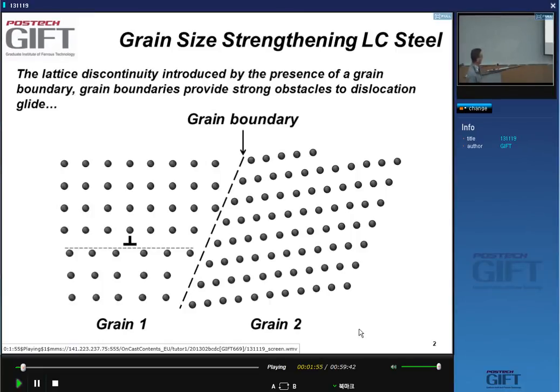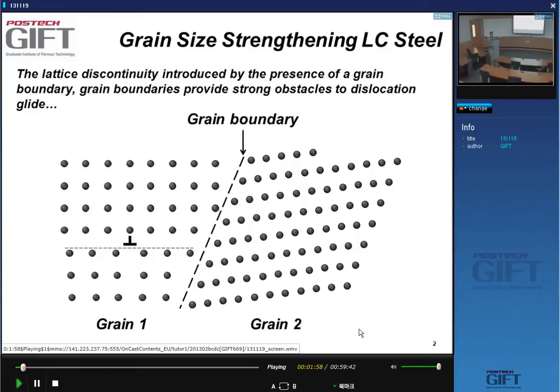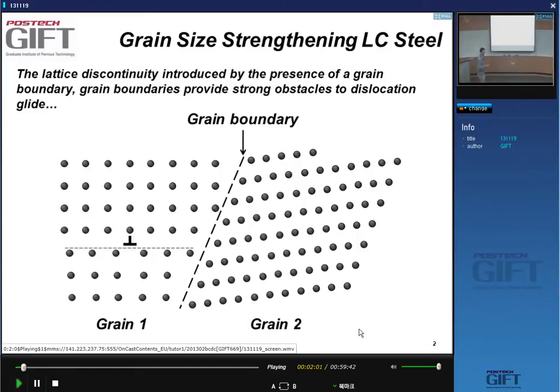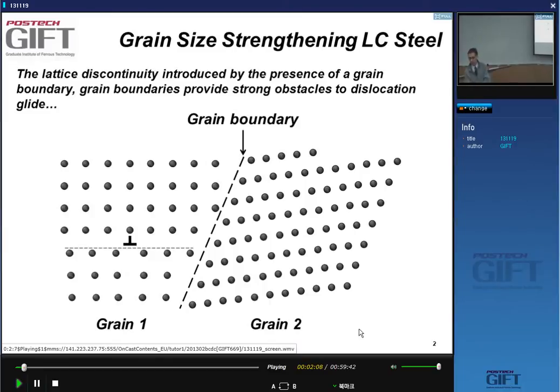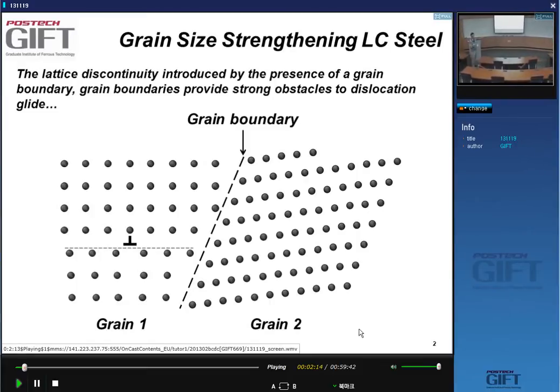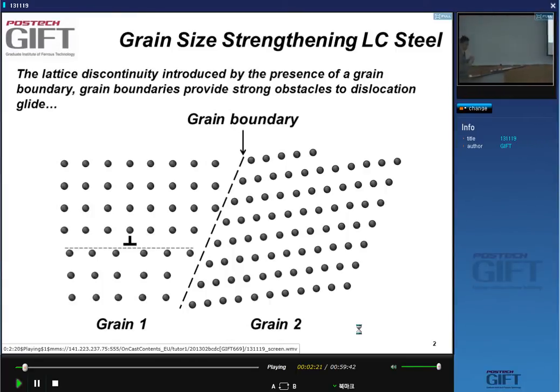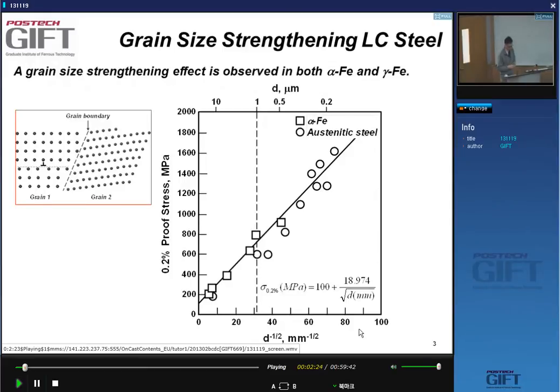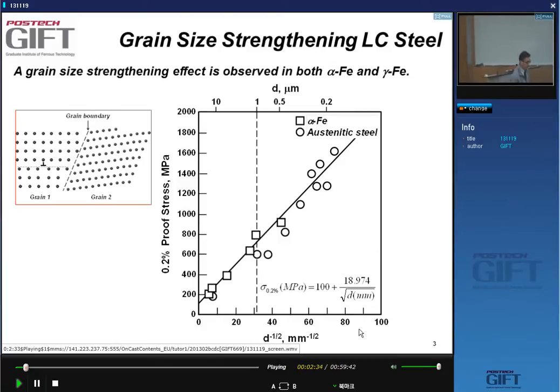It's very difficult for the dislocation to cross the boundary. It can happen, but the boundaries then need to have a very specific crystal structure of themselves to allow for the dislocations to actually cross the boundary, and that often involves dislocation reaction. We'll think of grain boundaries as very strong obstacles, and we'll come back to the importance of misorientations between boundaries in terms of how strong the strengthening is.